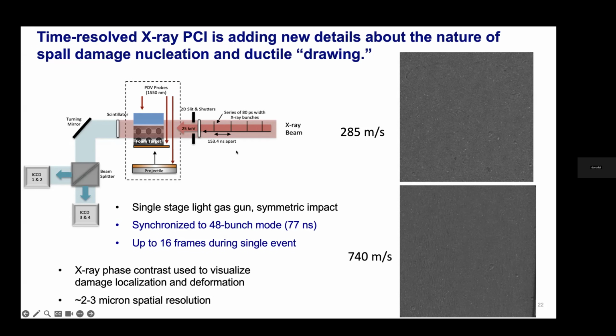So in these experiments, again, you're bringing X-rays from the synchrotron, you're passing them through your material to a scintillator, and then you have intensified CCD cameras, and now we can take up to 16 frames during a single shock event. Orthogonal to that, you're using a gas gun to launch your projectile into your target. In this case, this is a foam target, but we are actually launching polymer impactors into our polymer sample. And then we watch in real time the spall damage forming.